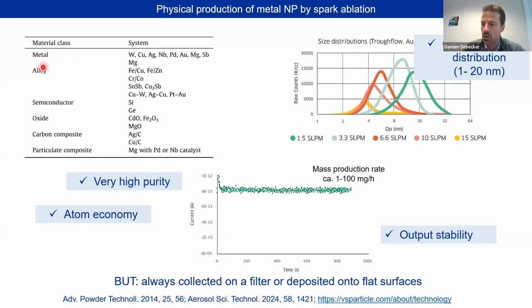You can also do it with alloys. So if the electrodes are alloys, you have alloyed nanoparticles. In some cases, you use one pure electrode and another pure electrode of two different metals, and you also get alloys. What is interesting also, especially for me in catalysis and in the perspective of fundamental understanding of heterogeneous catalysts, is that depending on the working conditions, you can actually choose the position of the size distribution that you can see here, targeting something closer to 15 nanometers or smaller, around 3 or 4. In some cases, they have been able to go even lower, 1 and 2. Okay, so that's very nice.